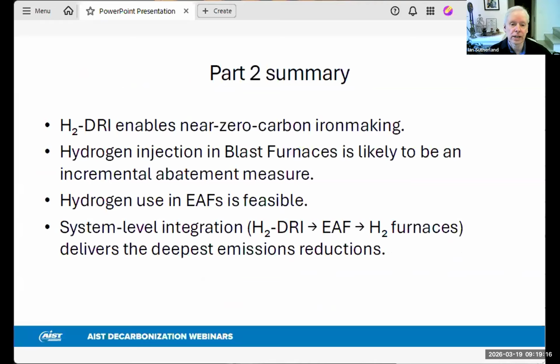So in summary for this section, hydrogen DRI enables near zero carbon iron making. Hydrogen injection into blast furnaces is really only likely to be an incremental abatement measure. Hydrogen use in EAFs is feasible, but it doesn't give a huge change in emission reductions. But it is that system level integration of hydrogen DRI, EAF, and hydrogen furnaces that will deliver the deepest emission reductions.